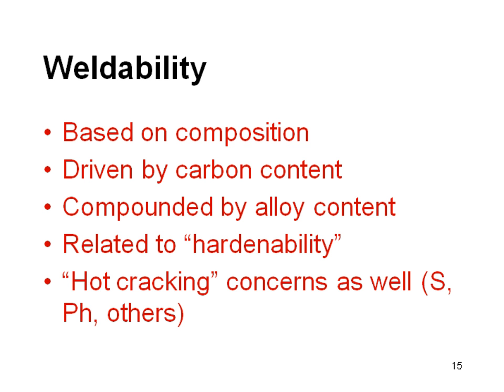Now, welding engineers are also concerned with something we would call hot cracking. We're pretty creative in our terms. We have hot cracks and we have cold cracks. Hot cracks occur when the steel is cooling for the first time. Cold cracks occur after the steel gets to below, let's say, around 200 degrees Fahrenheit. Hot cracks have to do with low melting point constituents in the steel, and two of the key constituents are sulfur and phosphorus. And so that's why we like to hold these alloys to maximum levels to make sure we don't get too much sulfur or phosphorus in our steel.